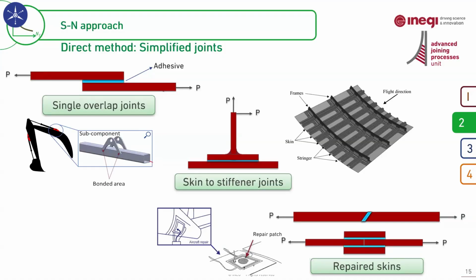While we are still in the direct methodology, we are trying to simplify it a bit more to reduce the costs, reduce the time, and also be able to test using universal testing machines. But the thing is that we are simplifying the loading conditions and boundary conditions, and we ignore the interactions of these joints with other parts of the structure. So when we interpret the data, we should take into account all these assumptions made in this type of direct testing.